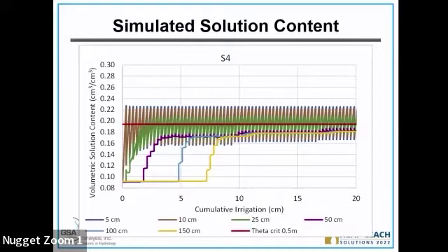That means they collapse the shallow structure. However, starting from around 25 centimeters, 50 centimeters, which is the purple line here, they stay well under the critical solution content. That means the shallow structure can get collapsed, but only to about 20-30 centimeters. But after that, the solution content does not meet the critical solution content. So they will try to hold the structure the best they can.